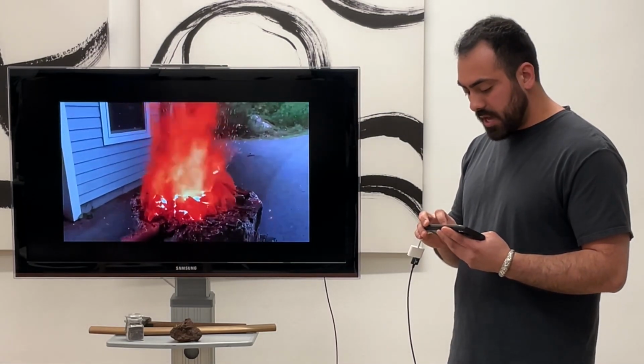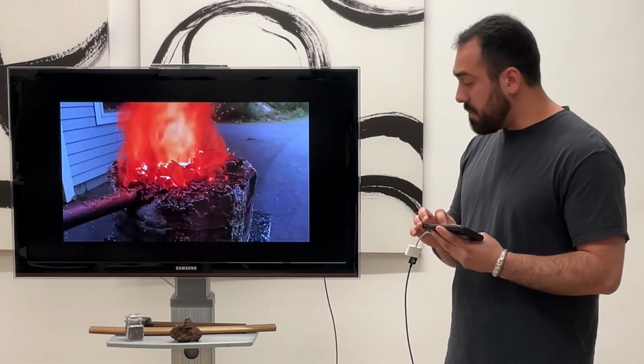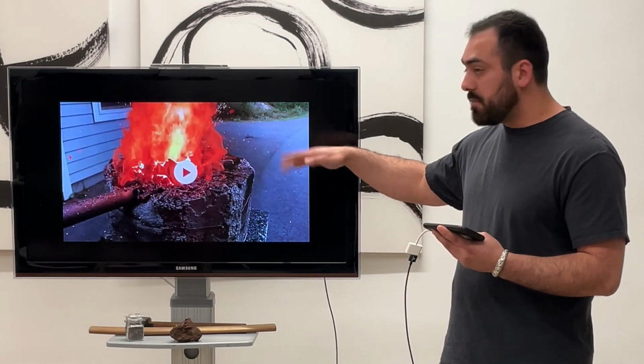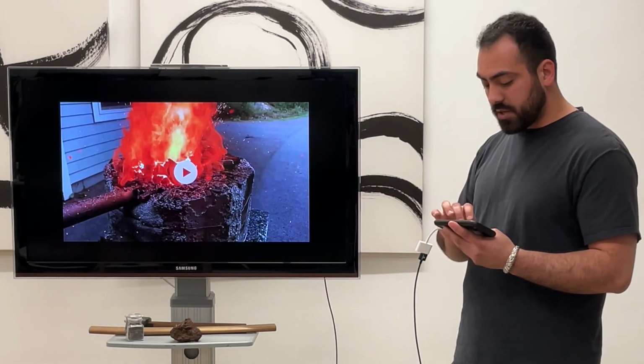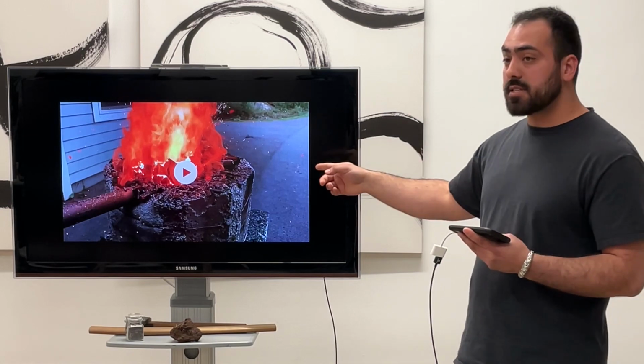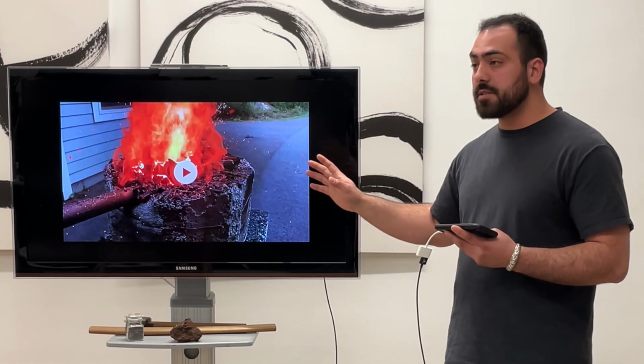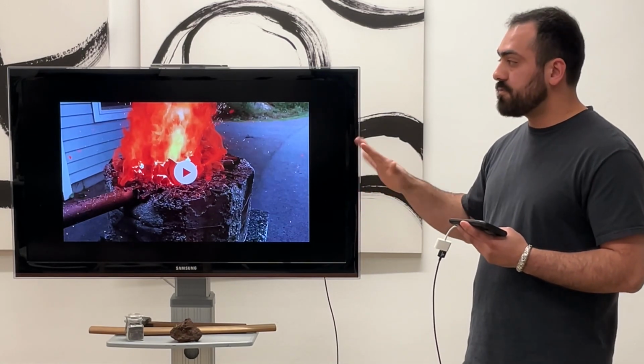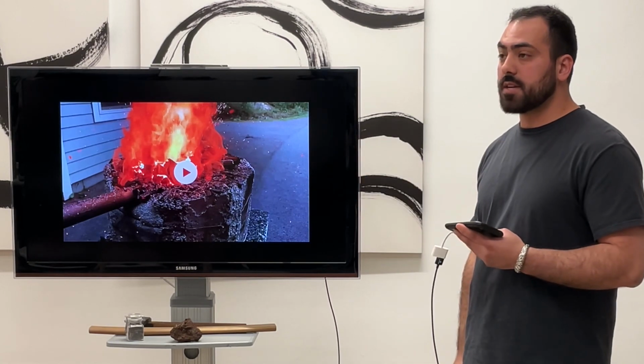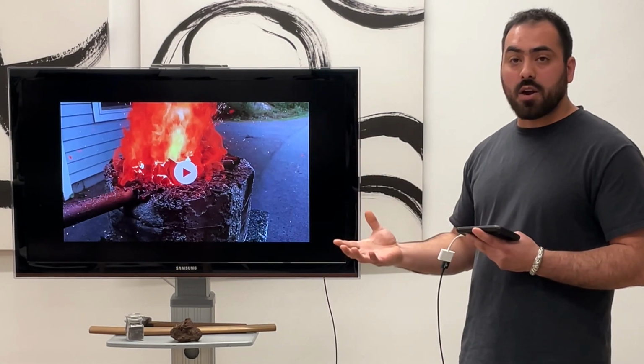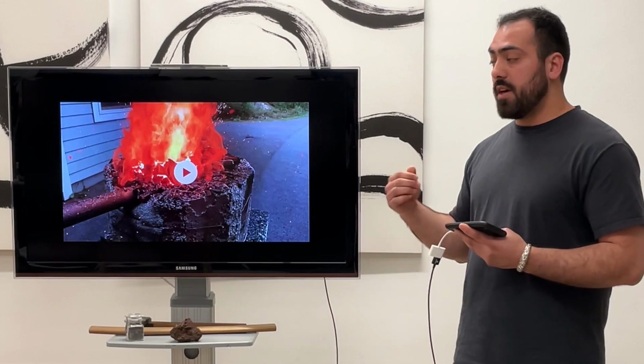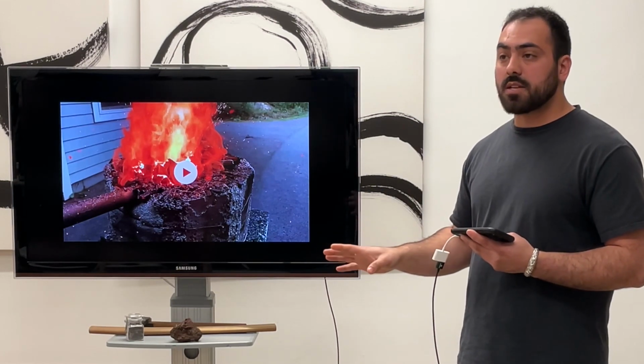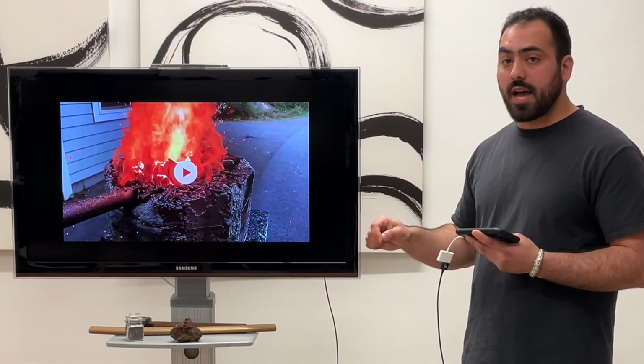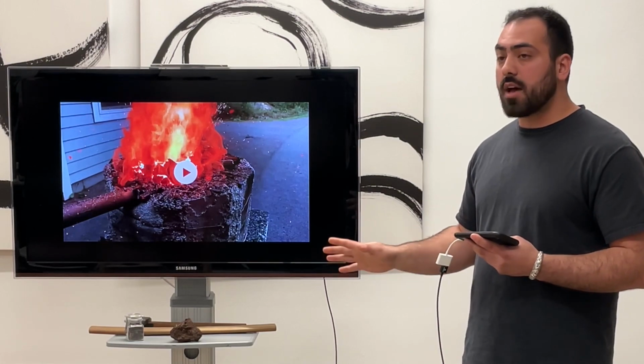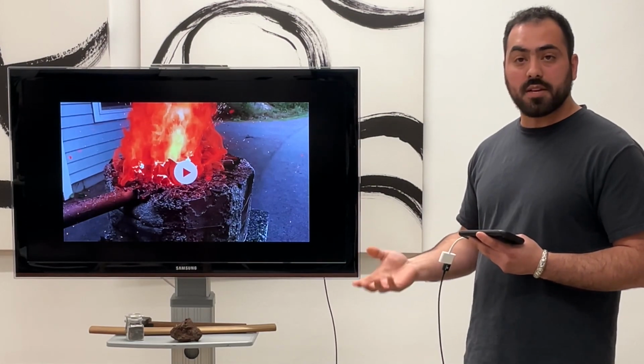Those sparks that you see coming out are the steel melting, and you see the bubbling of the charcoal over top. This process, instead of 4 to 6 hours, takes 20 to 30 minutes from start to finish. And you can make very high carbon, very nice steel. When it's folded, it's almost completely indistinguishable. Unless you were to do a metallurgical analysis of this stuff, you would not know that it's a different material, which I think is pretty cool.